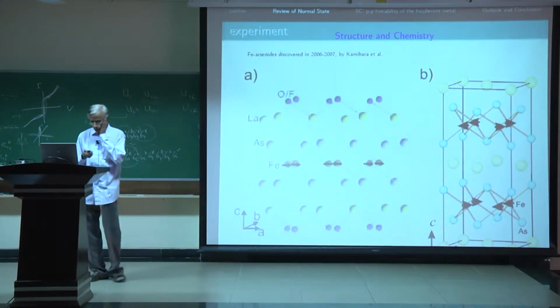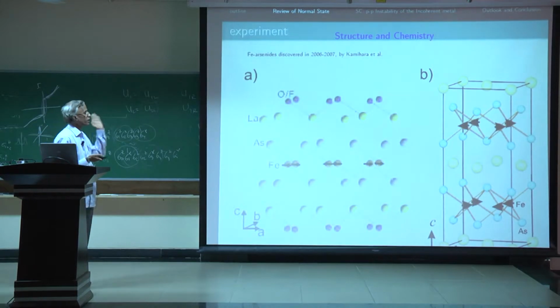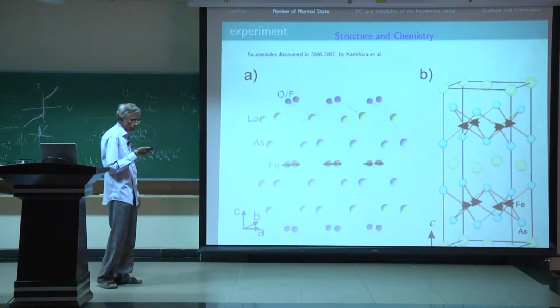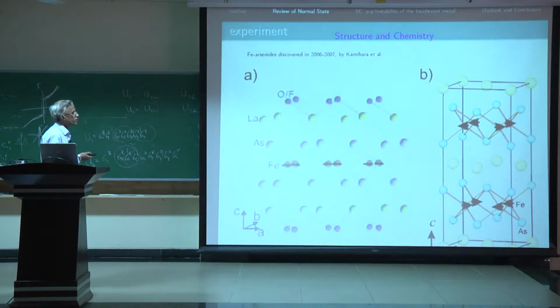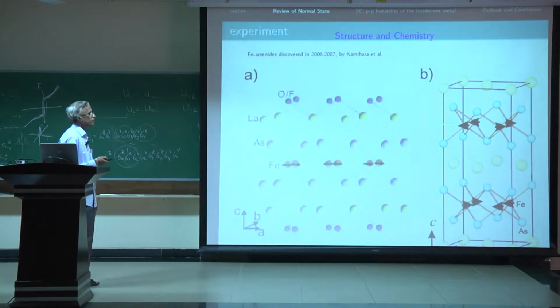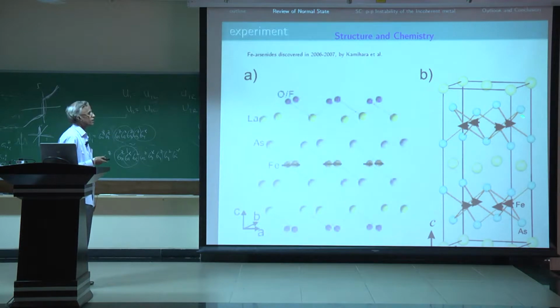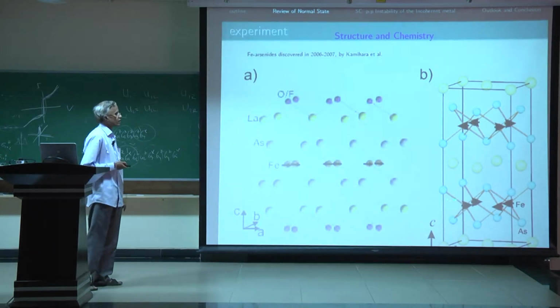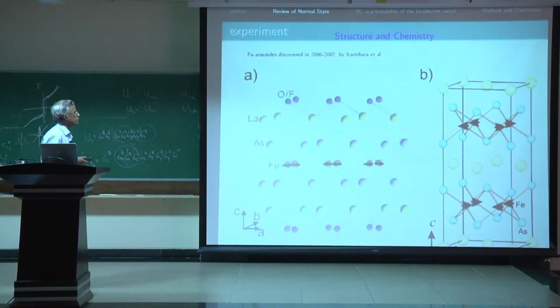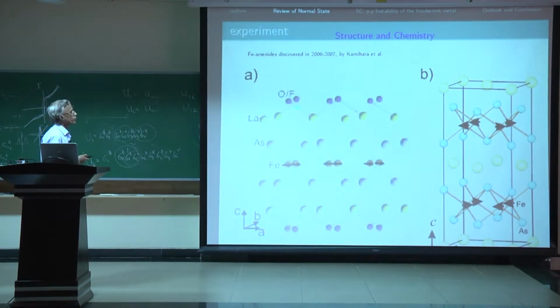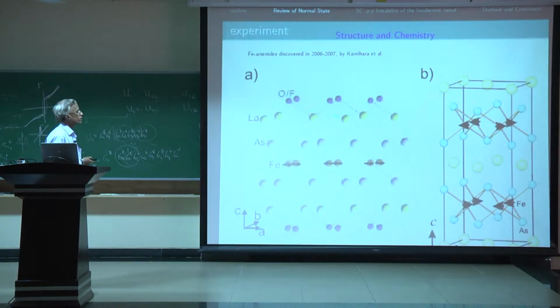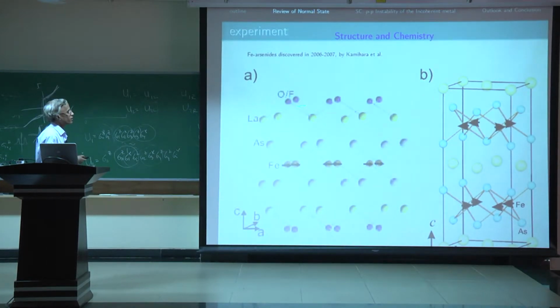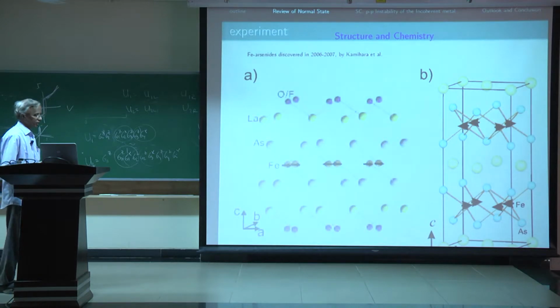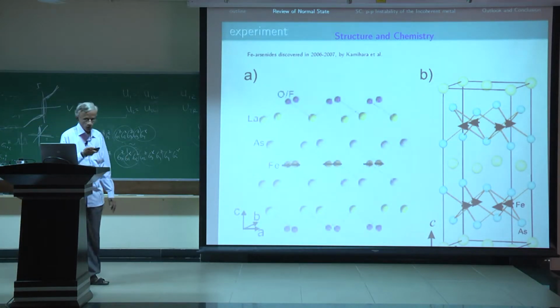This is an example of the crystal structure of iron arsenides. These are, in analogy with cuprates, layered materials, but less two-dimensional than the cuprates. The basic unit, which is basically the active space, are the iron arsenic layers with spacers of lanthanum, oxygen, where the fluorine doping occurs. So as in the cuprates, the doping can sometimes occur in the spacer layers, not directly in the iron arsenic plane, though in the 122 materials, one substitutes cobalt in place of iron directly in the planes. However, that's a magnetic impurity, not a non-magnetic one.